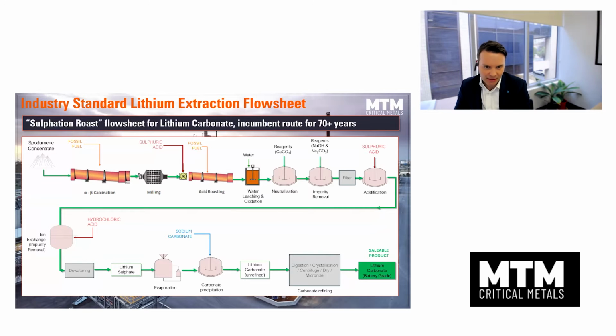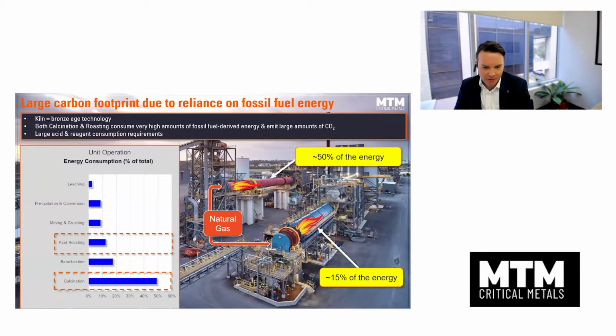Next slide, please. Now, just to put some numbers on it, including the mining of the ore, blasting, crushing, etc., 50% of the total energy you need per ton of finished product goes into that single calcination kiln. And that involves cooking the material at 1100 degrees for 3 hours. And the only source for these horizontal kilns is fossil fuels currently. So that's a lot of fossil fuels, it's a lot of CO2.